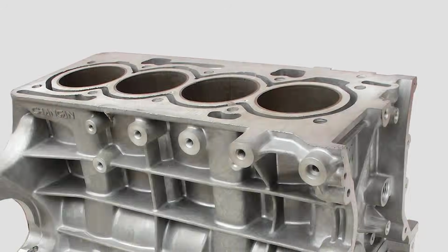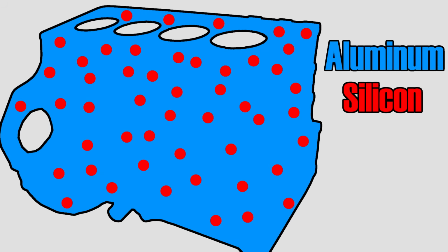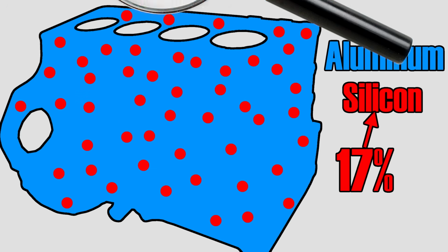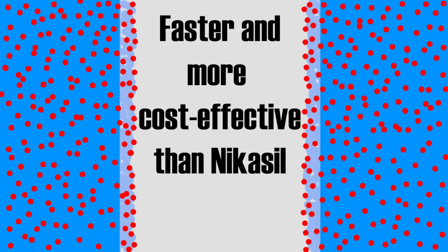You cast the entire engine block with a very high content of silicon, usually around 17%. Once the block is cast, you either chemically or mechanically etch away the aluminum in the cylinder, and so what remains exposed is a layer of silicon. And silicon is a durable and hard-wearing material. Overall, the process is much faster and more cost-effective than the electroplating complexities of Nikasil.